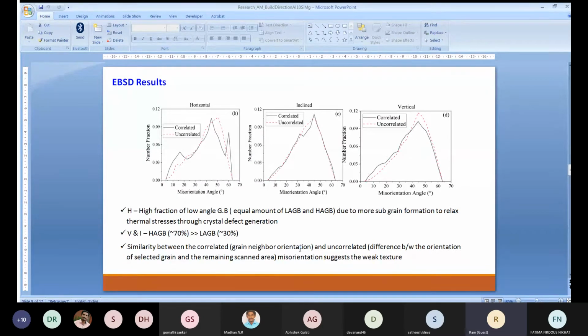Further, we didn't leave it there. We tried to understand from the EBSD results the grain misorientation angle, the grain reference orientation deviation, and the kernel average misorientation. These are the information you have pulled out from the EBSD results. The first one is the grain orientation, the misorientation angle study.